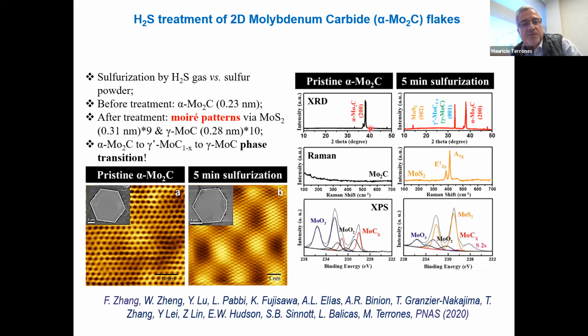So after 5 minutes of sulfurization in the XRD, you start to see the moly sulfide coming, and the gamma prime and gamma moly carbide, besides the alpha moly carbide. So you start to see new phases of the moly carbide, and that's quite interesting. Then you have the Raman, so you see the moly sulfide, right? And then by XPS we can see the moly oxide, moly carbide, and moly sulfide, as well as the moly oxide peaks.